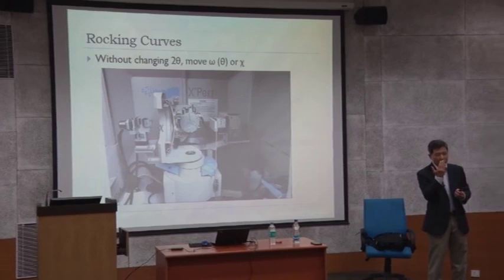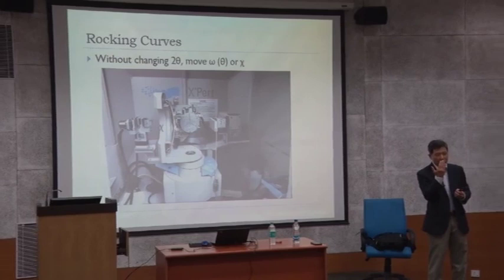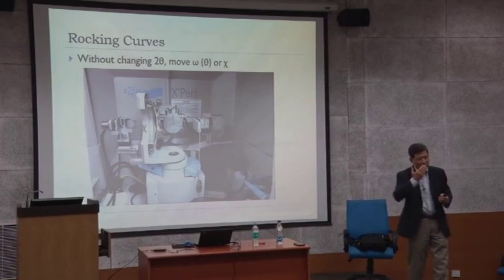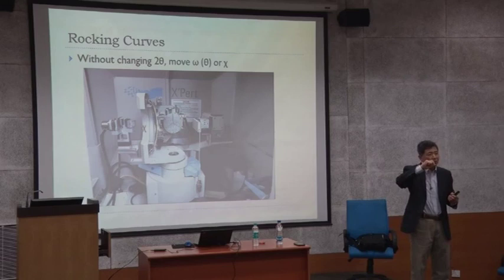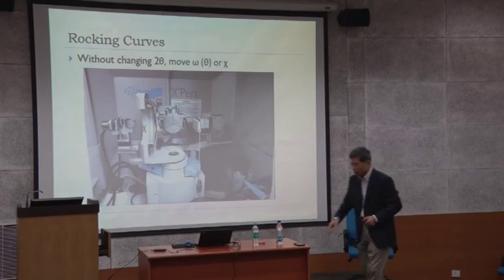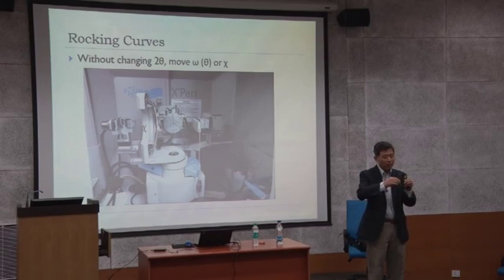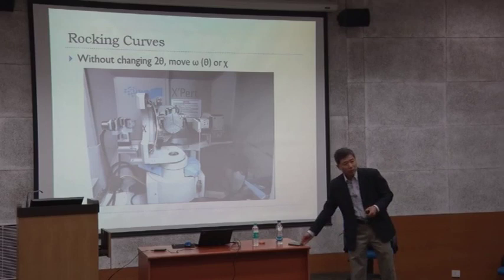Because you have to mount your sample and align it to find the Bragg condition — move this rocking and find the position. That's why with thin films you need to do that. If you cannot do this by automatic means, then you have to mount your sample using what you call a goniometer head — which means you manually tweak a little bit and find the position of the rocking. Your Bragg condition is always at half of the two-theta center.